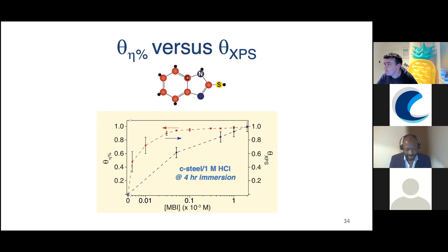Yeah, thanks for clarifying. Okay, next we have, what are your thoughts on corrosion inhibitor persistence, particularly as it relates to the dangerous versus non-dangerous corrosion inhibitors? So I think it's a very interesting idea, inhibitor persistence, which isn't really explored very much, because in most academic papers the focus is on increasing efficiency. Efficiency is looked at as the main indicator, because we already have very efficient inhibitors. So there's a very small window for improving, okay, maybe at higher temperatures, for example, but under standard conditions, we already have highly efficient inhibitors. So you're really in a very difficult scenario when you're trying to improve that by selecting another inhibitor. Whereas persistency, I think there's a very long way to go. That's an area we should be particularly targeting.